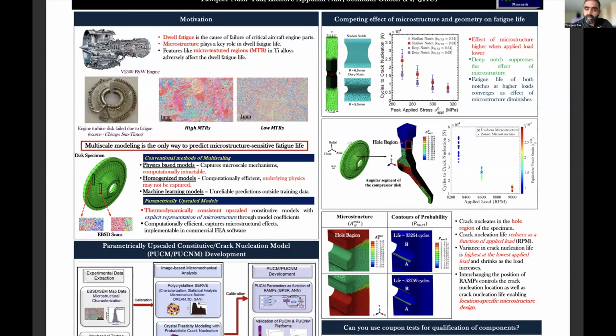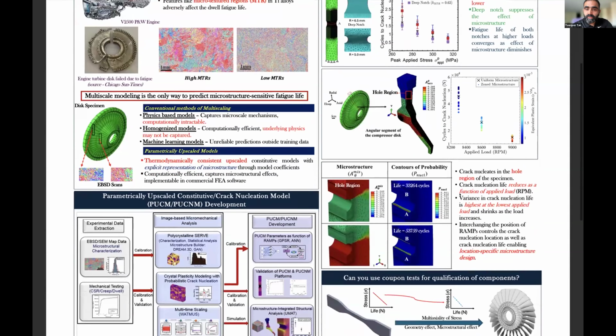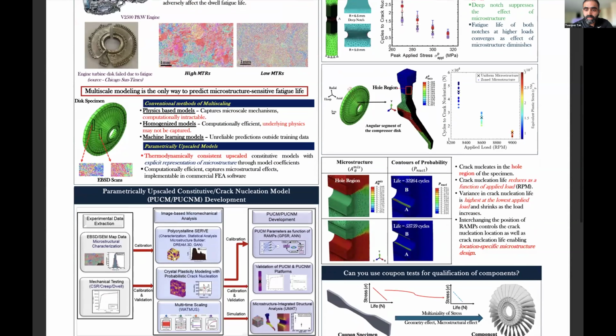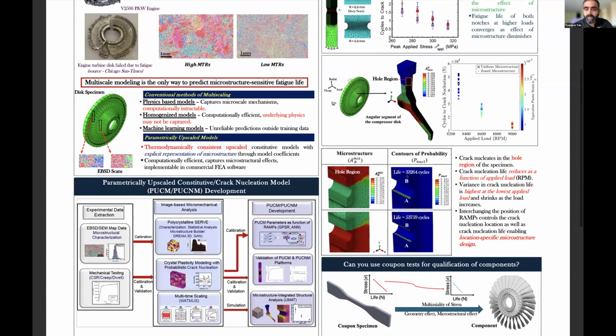Whereas when we take different combinations or permutations of these microstructures, we see that at lower loads, the sensitivity to microstructure is much higher. And as we increase the load, the sensitivity to microstructure comes down. In addition, we also observe that when the underlying microstructure changes, the crack nucleation life in certain cases rises from 33,000 cycles to 53,000 cycles. And also, we can notice that in one case, the crack nucleates at a different location.